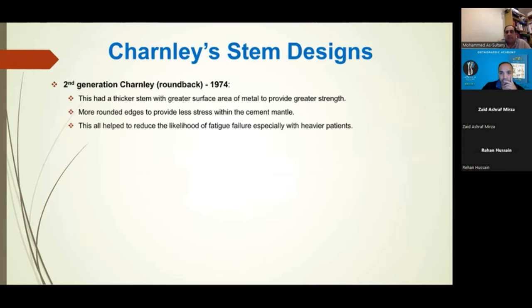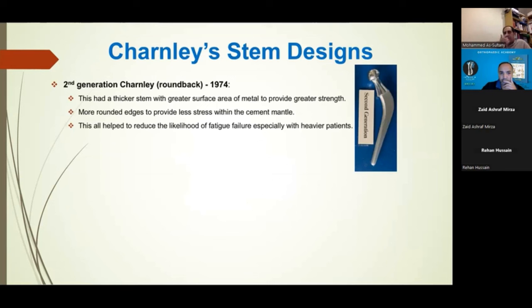Then the second generation was 1974, so it's quite a big gap. And this one, as you can see, had a thicker stem, the idea of greater surface area to give it more strength around the shoulder. And then the actual edges were more rounded so that there was less stress transmitted to the cement mantle to cause fatigue failure, especially with heavier patients.